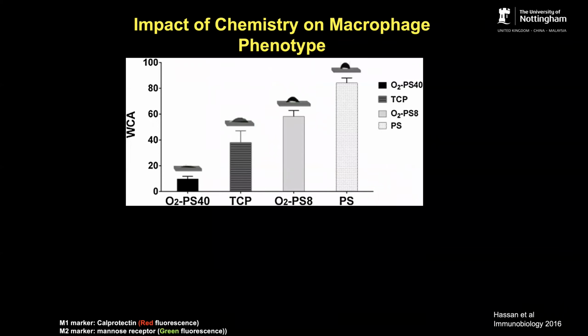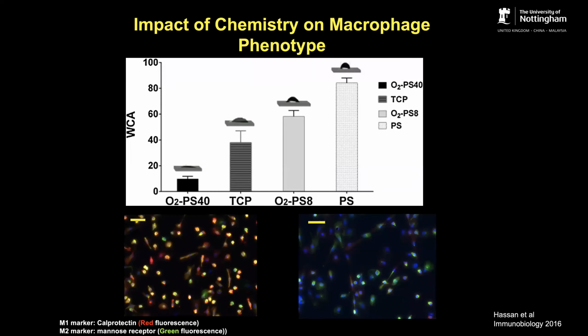A number of years ago, when we started asking the question of whether the surface chemistry could influence macrophage phenotype, we decided to modify the surface of tissue culture polystyrene using plasma etching to simply change the wettability. Just as a readout, obviously, that will also have other influences on the surface properties. But by doing that, we were able to generate surfaces that were highly hydrophilic, as opposed to ones that were highly hydrophobic. And that simple change in the surface chemistry would allow us to change the phenotype of monocytes. These are human primary monocytes that are seeded on these different surfaces and allowed to differentiate into macrophages.